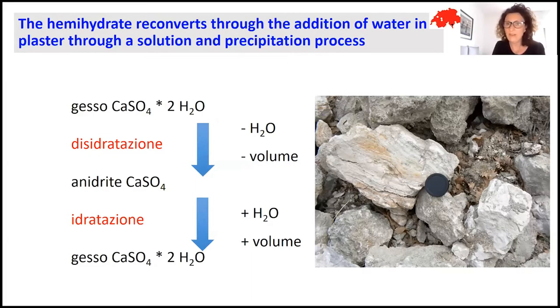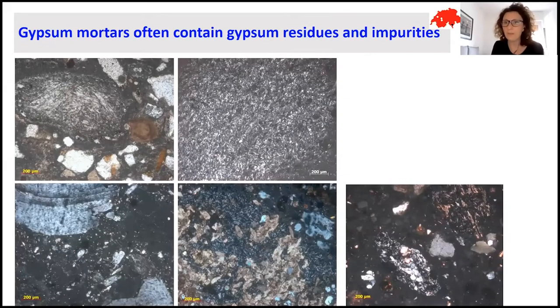With the firing, the crystal bound water is lost. So these 2 molecules of water are lost, and the anhydrite is obtained, so calcium sulfate without water. Then with the addition of water, we have the setting process of the gypsum. It's very important to note that with the setting process, the gypsum increases in volume because of the water uptake. And this is very important because I can be aware of the use of aggregate, as we will see.